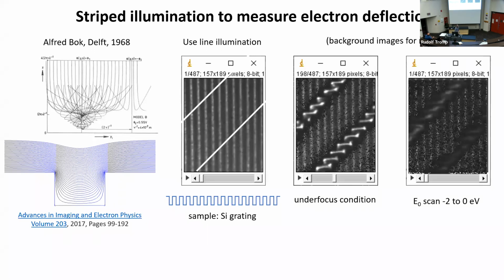And if we change the distance by which we turn around, so how close, when we turn around far away from the sample, this is a straight line, because this field has damped out, it drops off exponentially. But when we get closer and closer, we see this cosine-like amplitude forming along the illumination slit. And finally, when we hit the sample, the contrast disappears. Right? What we probe is the electric field strength outside the sample in vacuum as a function of approach distance.